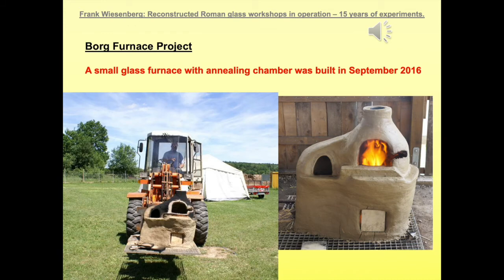Well, here you can see the reason for the metal grid. I had to relocate this furnace a couple of times. So we probably invented the first traveling Roman-style glass furnace whatsoever. Just a joke. In my opinion, there could be some evidence for some fire pits in keyhole or pear-shaped of about 60 centimeters of length, which could be used for glass working. So it could have been done in Roman times, something like this, but definitely not on a metal grid.